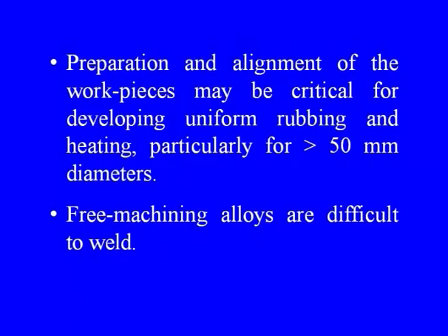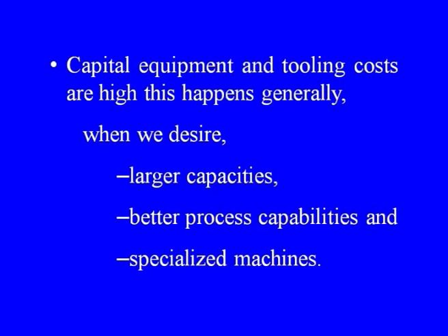Preparation and alignment of the workpieces may be critical for developing uniform rubbing and heating, particularly for pieces having diameter more than 50 millimeters. Free machining alloys are difficult to weld by this process. Capital equipment and tooling costs are high. This happens generally if we desire large capacities, better process capabilities and specialized machines.